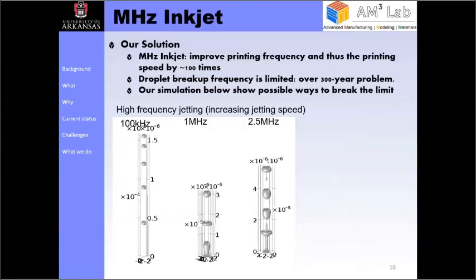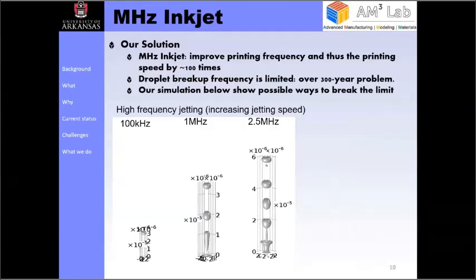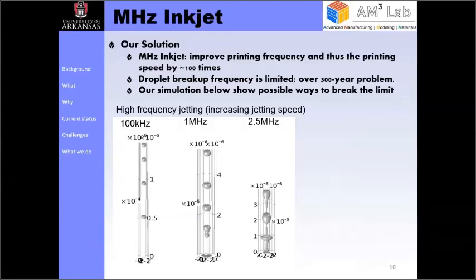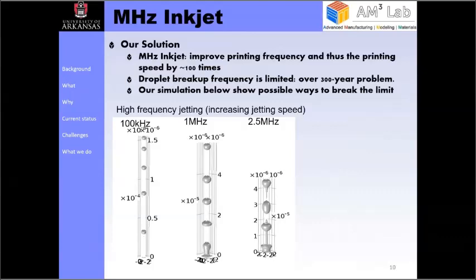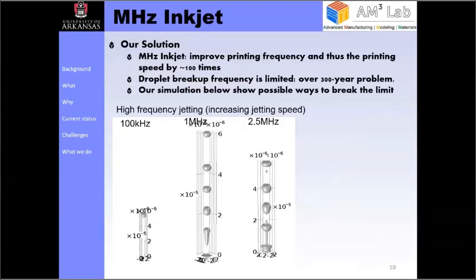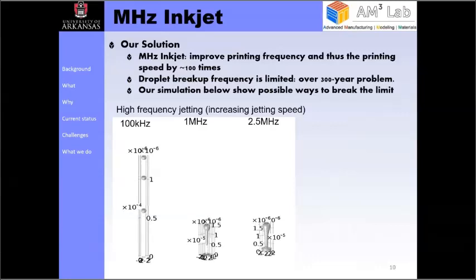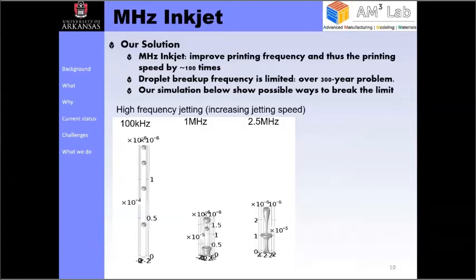It's a very old problem, because the fundamental physics resides in the droplet breakup, which has been studied since the age of Newton. What we have done is come up with a hypothesis that if we increase the jetting speed, we can hopefully overcome this limit, which is limited by the surface tension force. And it's very difficult to increase the surface tension force to increase the printing frequency. So what we did is increase the jetting speed, and we have done some simulations which show we can improve the printing frequency to megahertz for sizable droplets.